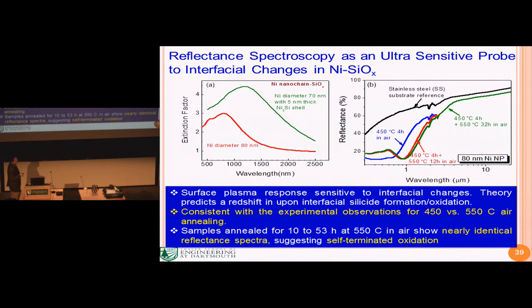So then we thought, okay, maybe we're going to completely oxidize this particle, which is only 80 nanometers in diameter. But interestingly, we annealed for 12 hours, and we can still see the nickel diffraction peaks from XRD. So Xiaobai decided to go another 20 hours at 550 degrees. We thought now it should be completely oxidized. Yet, actually no, because you see the spectrum is almost identical in this case.